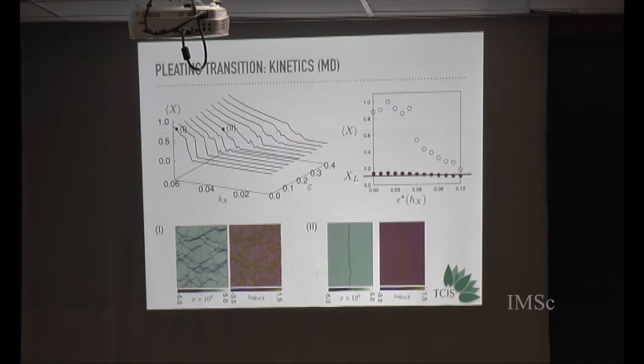So the other thing that I find very interesting is that when this dynamical transition happens, the value of this non-affine parameter is exactly this saddle point value. So as soon as the crystal reaches this saddle point value, it transforms. So there is an equilibrium transition and then there is this dynamical transition.